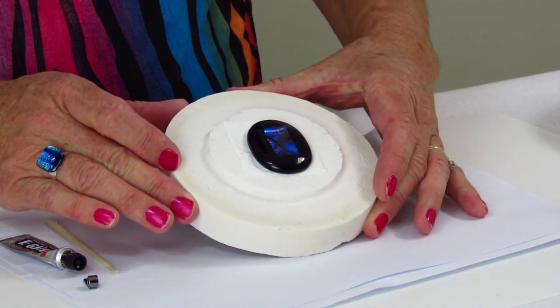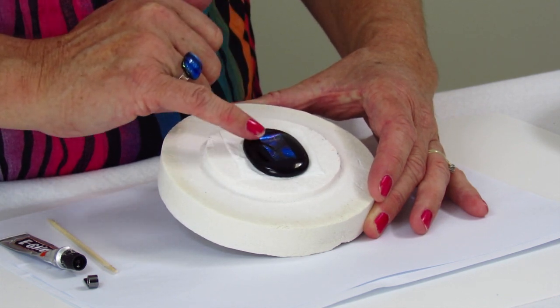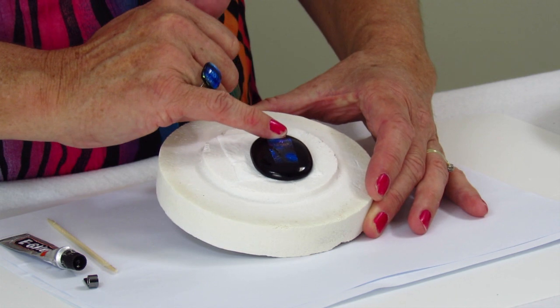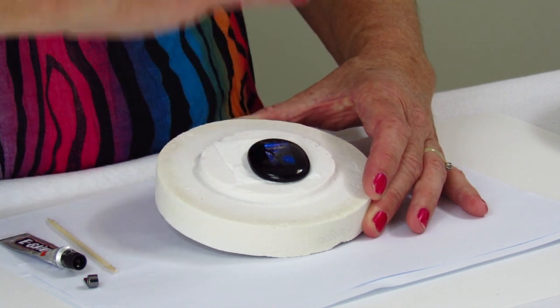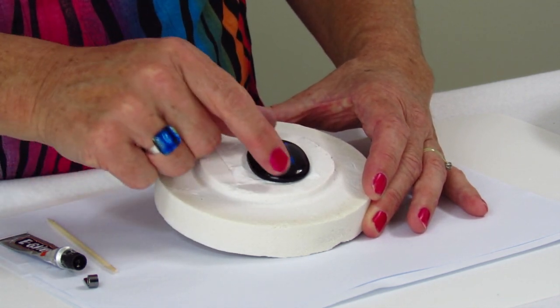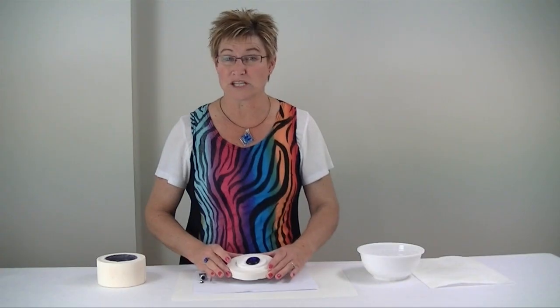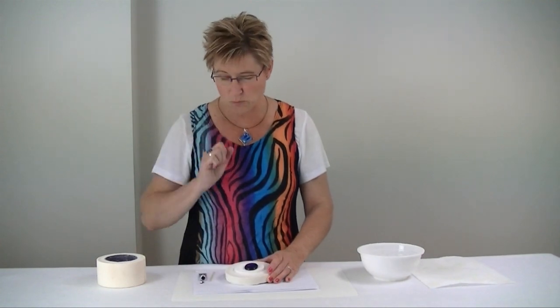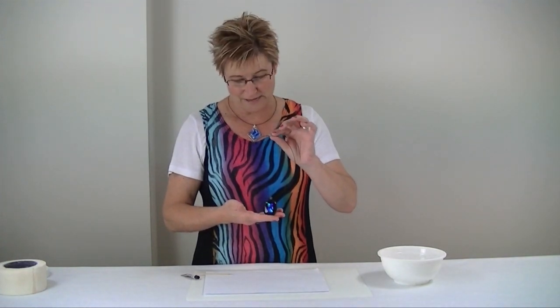Our glasses will cool down now too so I can touch that. It's gone a little bit strange here — perhaps I didn't quite cut that clear quite long enough, a little bit short, and it seems to have shrunk up towards the dichroic piece there. We also seem to have a little bit of splitting of our dichroic there, which indicates to me that maybe we over-fired it just a weeny bit, but not too bad at all. And there is our pendant — that's really lovely. Great success today. So, thanks for watching. You can watch more of our videos on our channel and don't forget to subscribe for regular updates.